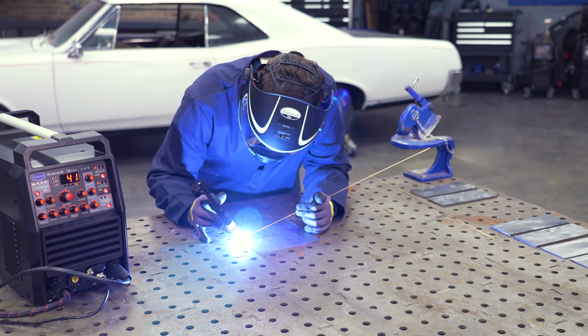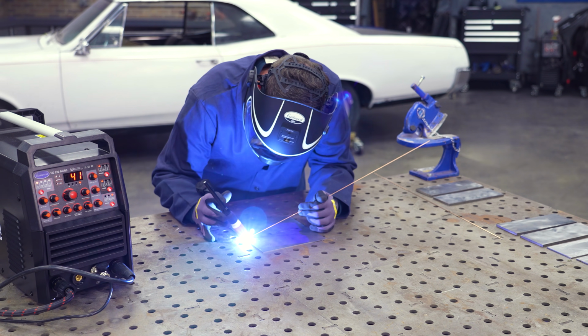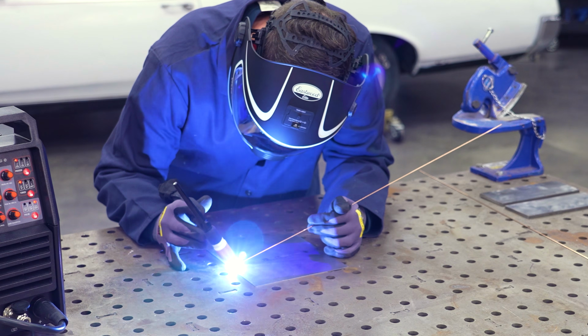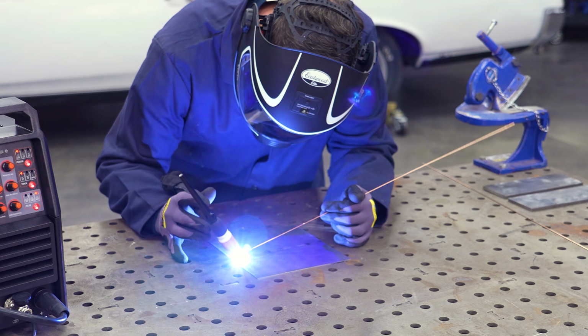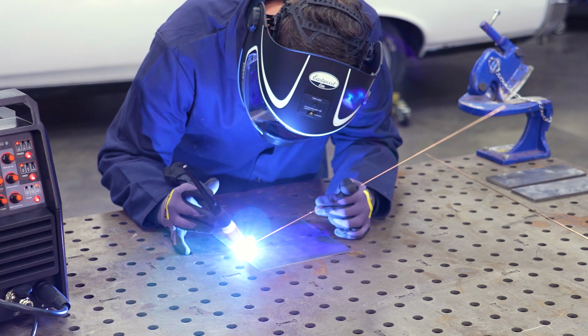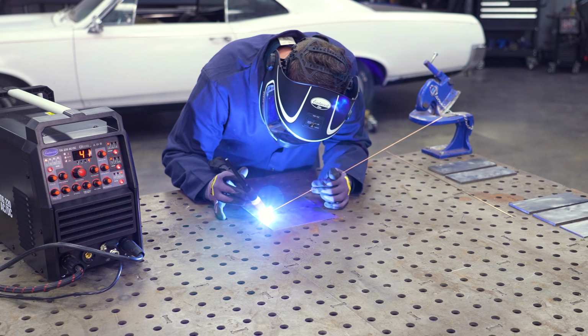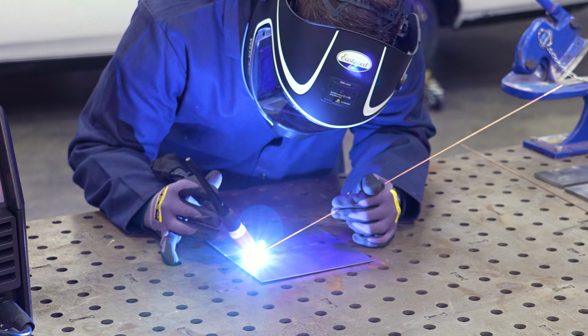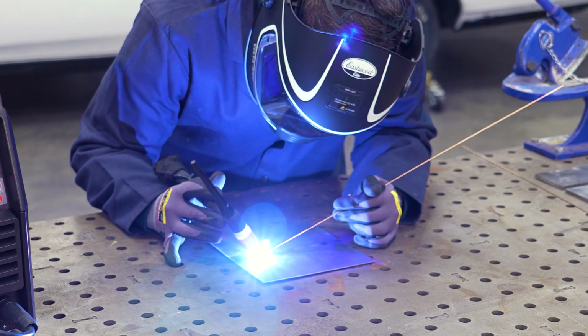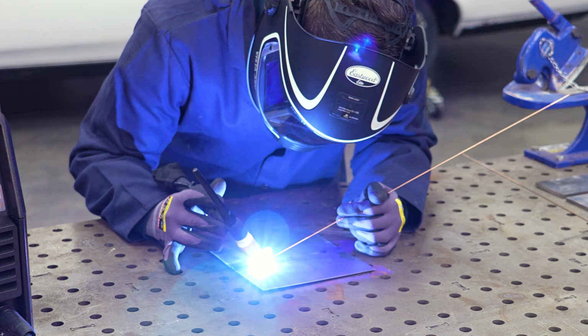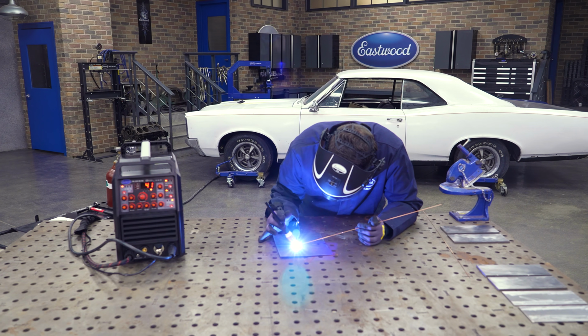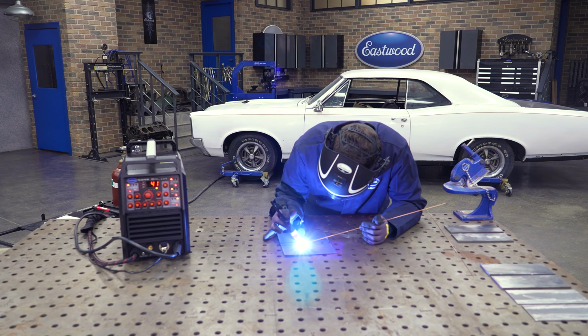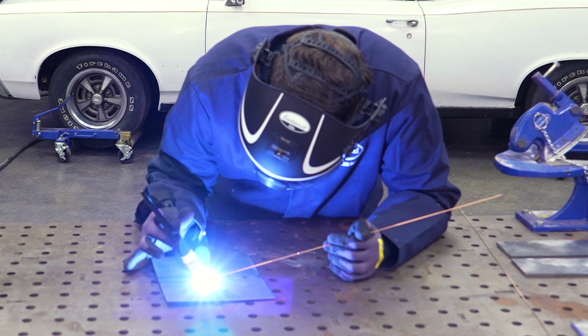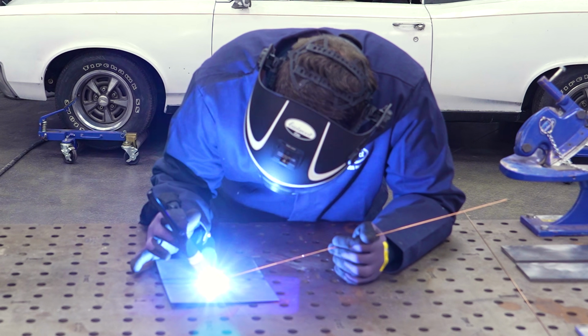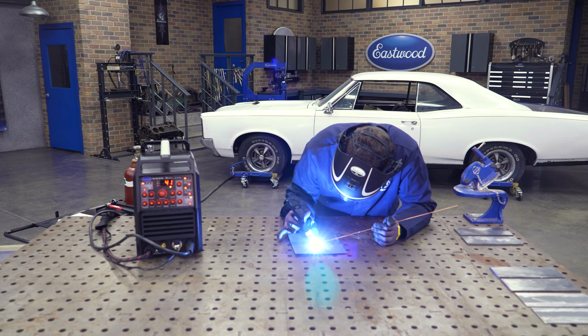Strike my arc. Wait a second for the puddle, and we're just gonna fly through. Another really nice feature of high frequency pulse: when you have a really crisp butt edge to weld, you don't always even need to use filler for thin sheet metal. In fact, it really likes doing that, mainly because you're not staying in one place too long for it to burn through. The benefit to that is less filler rod means less material, which means less metal to warp when it expands and contracts, and an easier planish for your weld.